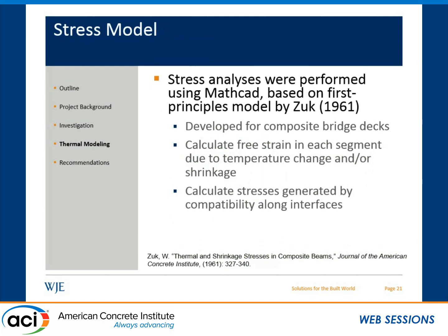The other thing that we did was look at stresses, and these are approximate stresses. We had to make a lot of assumptions in our model because we don't have a lot of the early age information from this bridge, or these bridges. But we did some basic first principles stress calculations based on the model by Zuk. And Zuk's model was developed for composite bridge decks. So essentially you have a girder and a deck. And the approach is you calculate the free strain in both the girder and the deck due to temperature change or shrinkage or both. And then you can calculate the stresses in the bridge deck using compatibility equations right along the boundary between the deck and the girder. So it's a very simple approach. It's based on very basic principles.